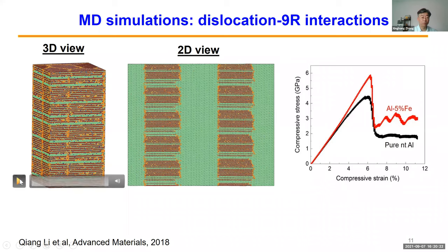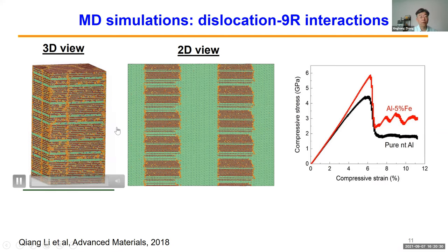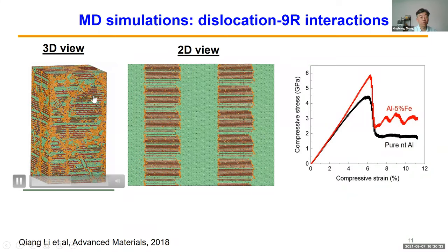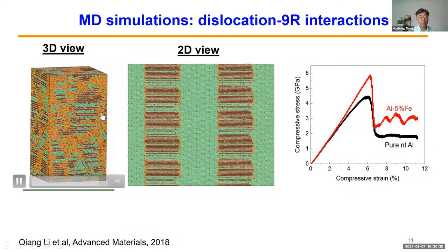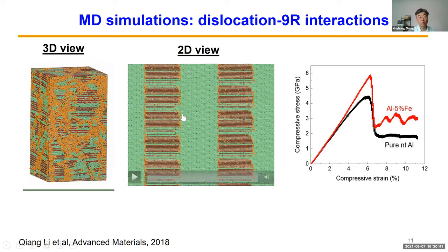Now if you do this MD simulation, introducing all these 3D stacking faults in aluminum iron, you can see the stacking faults evolve very quickly. The orange color shows some unidentifiable crystal structure. So this is how the nanotwin aluminum iron should deform. The 2D view shows it a little better, in the sense that you can see things in a clear way. Again, green is the aluminum iron matrix, and the red is the 9R columns. These are the columns filled with stacking faults, the 9R phases.